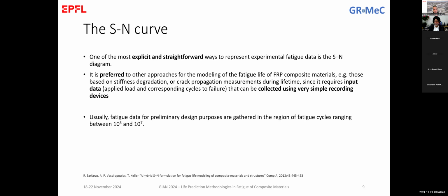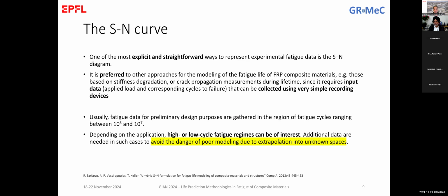We try to develop S-N curves in a region of cycles between more or less 1,000, so 10 to the power of 3, and 10 to the power of 6, so 1,000,000 cycles. Specific applications might need more or less. So materials used in wind blades, for example, we know from aeroelastic measurements that the wind blade material can see more than 10 million cycles during their fatigue life. So there it is probably interesting to do testing at the high cycle fatigue and reach 10 to the power of 7, even 10 to the power of 8 fatigue cycles during the experimental investigation. And this will allow to avoid problems with poor modeling due to extrapolation into unknown spaces.